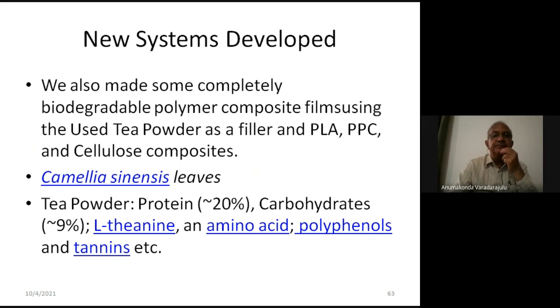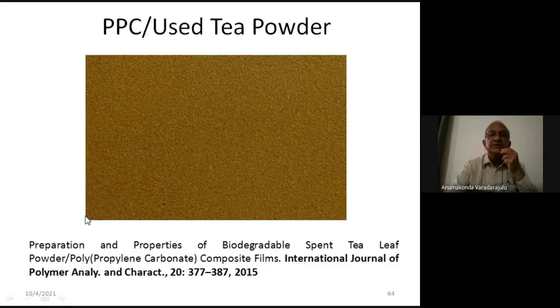Then we used this in used tea powder, because used tea powder has these particular components: proteins, amino acids, polyphenols, tannins, etc. They will not go out, even after brewing; they remain there. So we used this in the polypropylene carbonate. So very uniform film here. Sorry, this we already published. They gave very good strength and higher thermal stability because of the presence of the polypropylene carbonate. Moreover, it lowered the cost because it is a waste material we used, and the cost has come down.